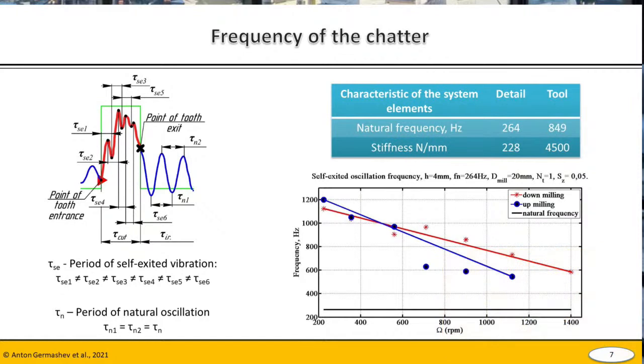We did some investigation and measured the chatter frequency during the cutting test. We did it artificially. We significantly reduced the spindle speed to reach the conditions where the cutting time is higher than the period of the chatter, of the self-excited oscillation, and we reached the conclusion that the chatter frequency changes significantly with the changing of the spindle speed, and even with the feed direction. So it's a different chatter frequency for up and down milling. And also this frequency is significantly different from the initial frequency, which also does not suit the classical regenerative theory. The next slide, please.